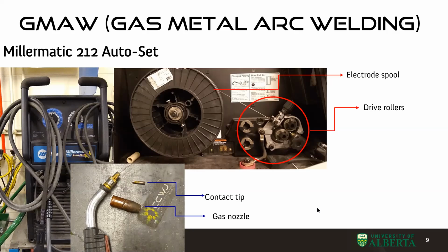That's why also if you cut the wire, it helps. You do away with the silicate. If you ever pay attention to the welding machines, when they stop the arc, they have a whole algorithm that ends up giving you a relatively clean ball. But that's in MIG. In subarc welding, you cannot do that because you don't have shielding gas.